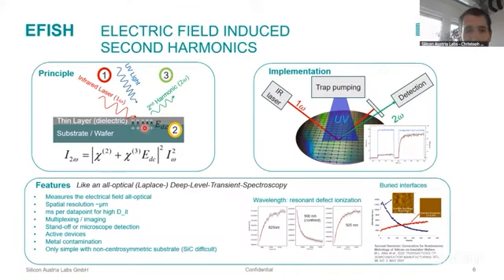And when you have defects at an interface, you can trap charges there. And this is exactly where the eFish plays into. So you have trapped charges at interface defects, and then you build up an electric field. And the electric field is especially strong due to the thin oxide layers that you typically have in the semiconductor industry, and therefore you get a lot of volts per distance. Yeah? And it doesn't really matter how you generate the charges, but you can either utilize the infrared laser that is later also used as the interrogation beam, or you can use UV light, rather weak UV light, to populate the electronic traps, or you can use an active device and measure in situ on an active device.